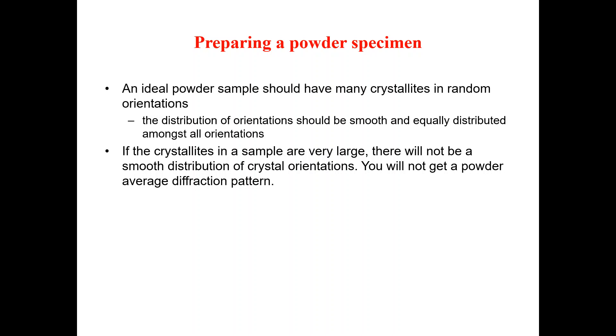Whenever you are trying to do XRD of a particular sample, you should make sure that the crystallite size is not very large. It is always preferred during XRD analysis that the crystallite size should be smaller than 10 micrometers to get good powder statistics.